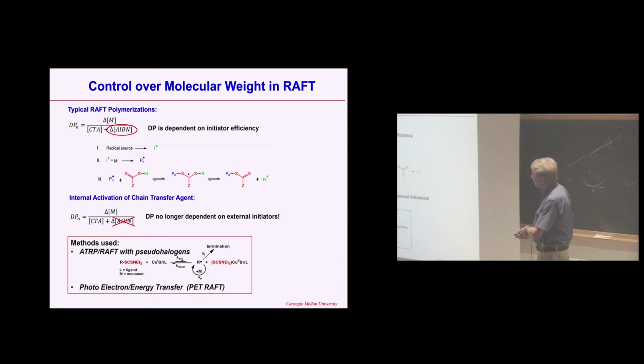So one approach is that you could use, for example, some copper as a catalyst to generate these radicals without generating new chains. So it would help photodissociation. And there is also some photo electron or energy transfer reactions, which under irradiation can also break this bond here and generate radicals without making new chains.